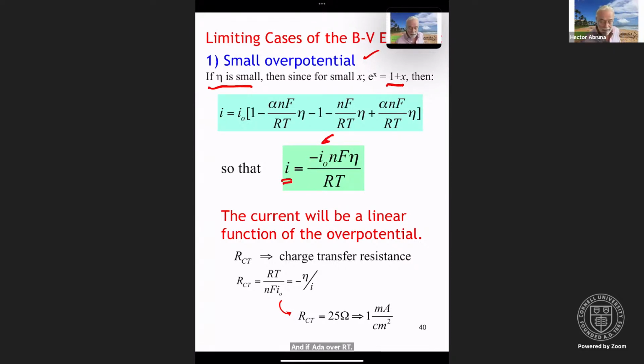Meaning that for small overpotentials, the current voltage relationship will be linear. And so we have linearized the Butler-Volmer expression. The current will be a linear function of the overpotential. We can take this a little bit further and using just Ohm's law, E equals IR, we can talk about the so-called charge transfer resistance.